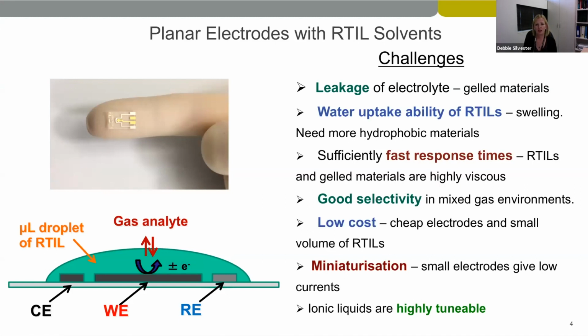But there are some challenges that come with changing the design of the sensor. So now we have what's called a membrane-free gas sensor. And so the challenges associated with this include leakage of the electrolyte. So we've got a droplet of a liquid, and we can overcome this by using gelled materials, and I'll tell you about that today. Anybody that's used ionic liquids before will also know that they take in water. So we really ideally need to look at hydrophobic materials because we need to have these gas sensors able to work in a wide range of humidities. We'd like a fast response time. A drawback of ionic liquids is their fairly high viscosity, which slows the diffusion coefficients. And particularly if we gel the materials, then we have very highly viscous solutions.